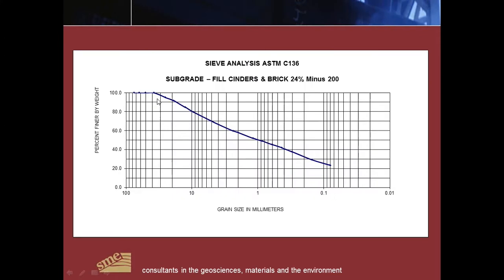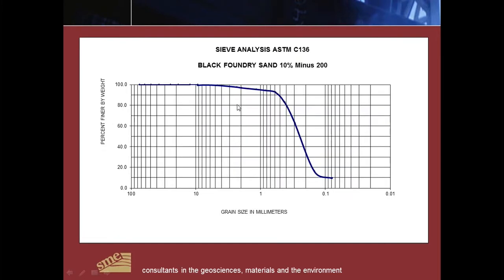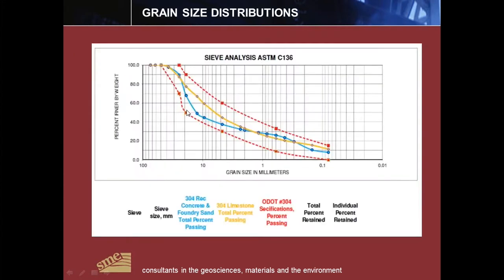This is a gradation curve for the subgrade material, showing that it is a well-graded cinder material that is predominantly granular. This curve is for the foundry sand constituent. It shows that the foundry sand is a poorly or uniformly graded material with about 10% fines in it. Again, typically our foundry sands run cleaner than this, but in this project we're using a certain source of material.